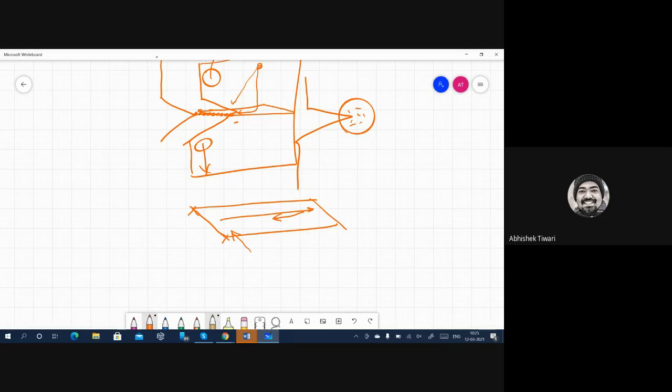So if a material wants to come from here, it will have to cover a huge amount of distance in comparison to a material which has to come from this side. So this material will come in more than from the back side. So this will cause a sinking of the crack tip. And you will see in the experiment that this happens at the crack tip.